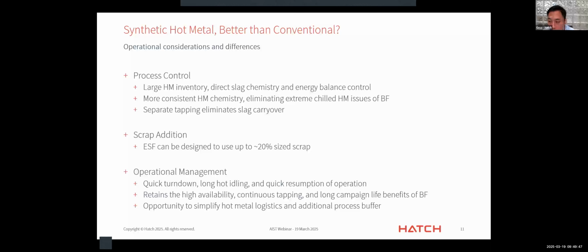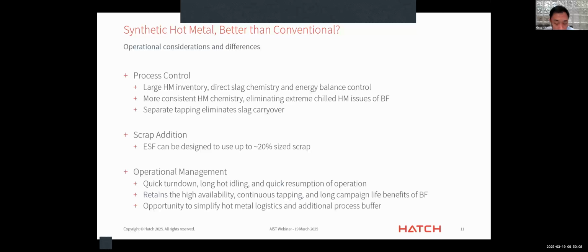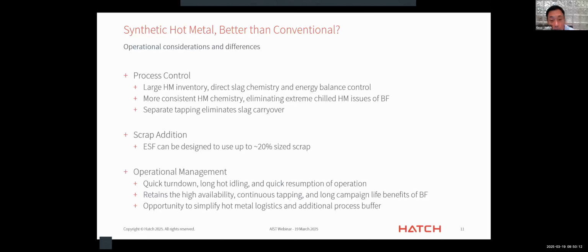And one thing that's usually overlooked is the scrap addition. The ESF can be designed to take up to 20% scrap. What that means is that, of course, there will be impact on the hot metal quality. But that will, I guess, deprioritize perhaps the need for fully saturated hot metal in terms of carbon. If you can use 20% scrap in the ESF, is there really a need to get a 4.5% carbon hot metal then to melt additional scrap?